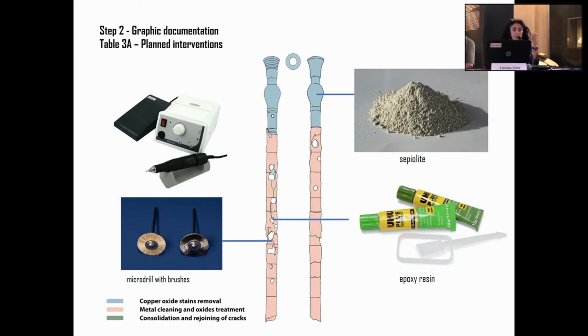And so it's better to eliminate the more aggressive superficial parts with a micro drill, with some very soft brushes, or even stronger steel brushes, but using them very, very slowly and with great attention. It's also possible, I didn't note it here, to use a very light sandblasting on the surface with, of course, very soft materials like wood powder, something very soft, to eliminate the crusts and the oxidation on the surface.